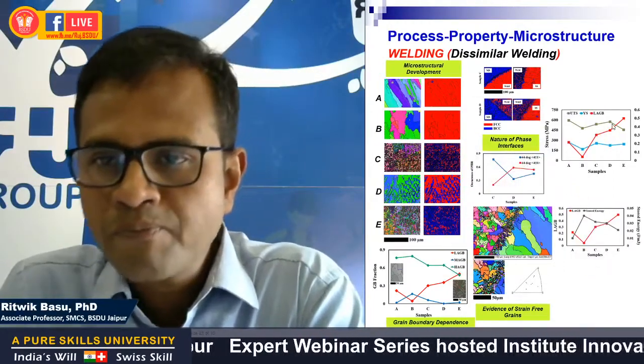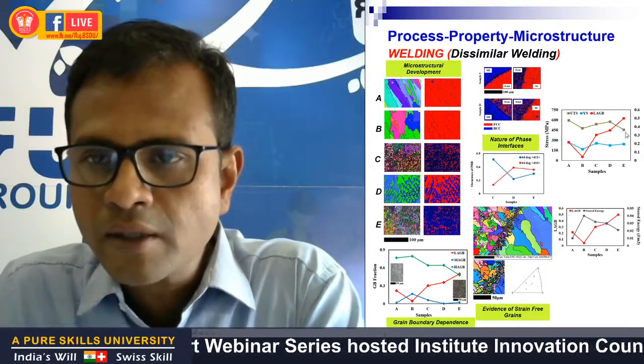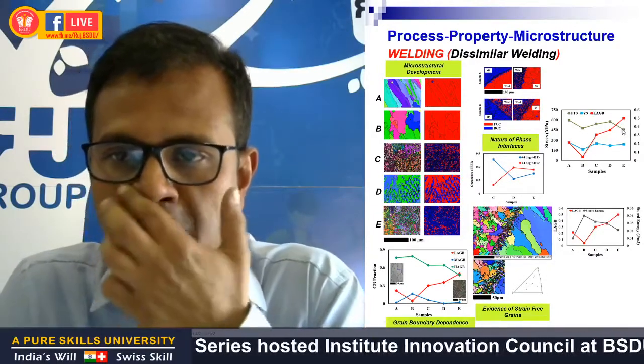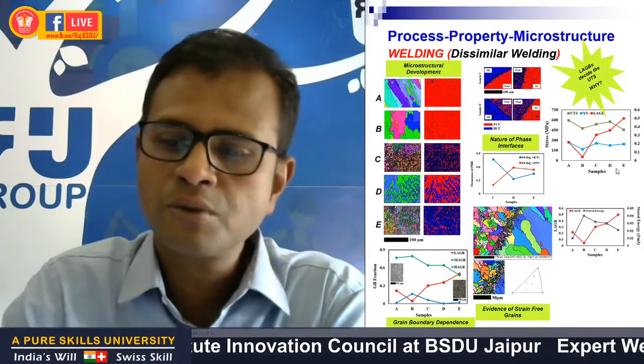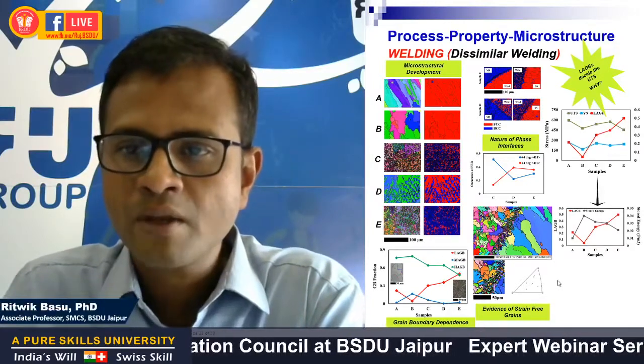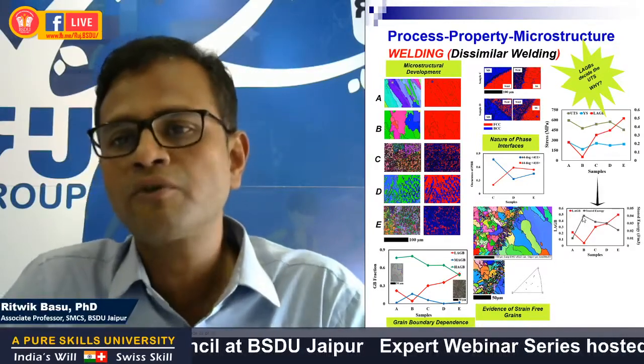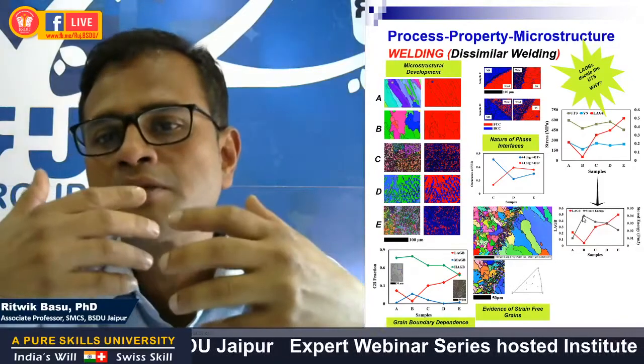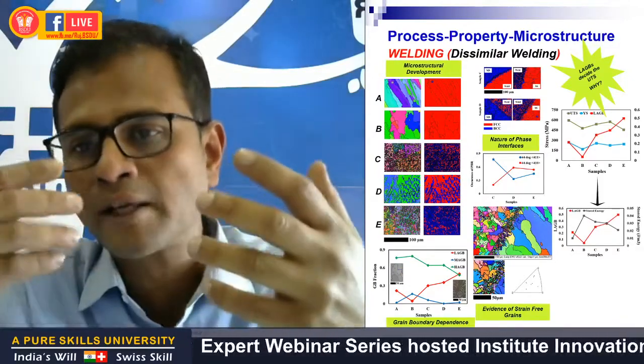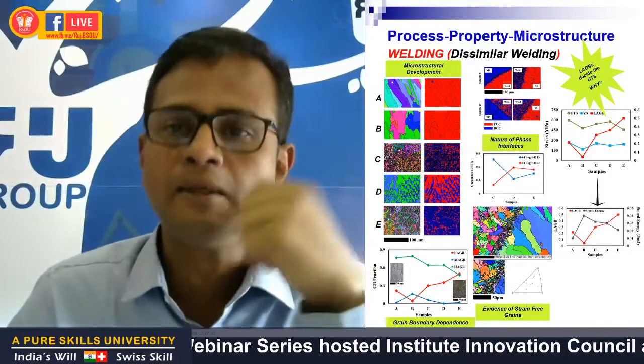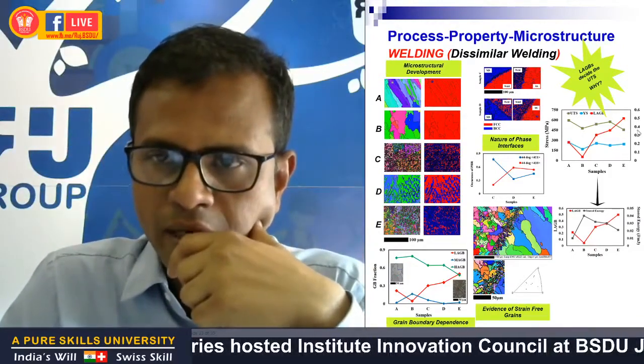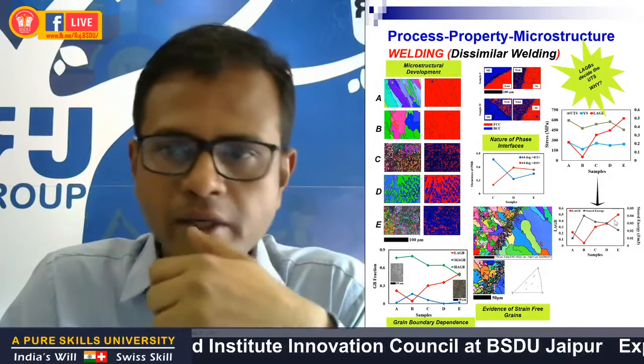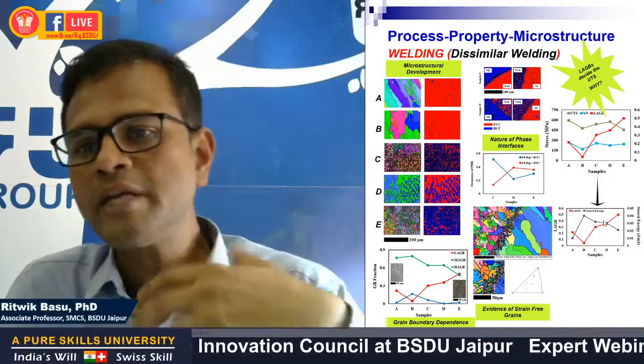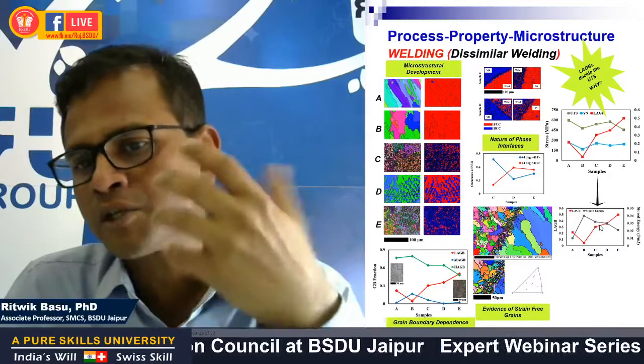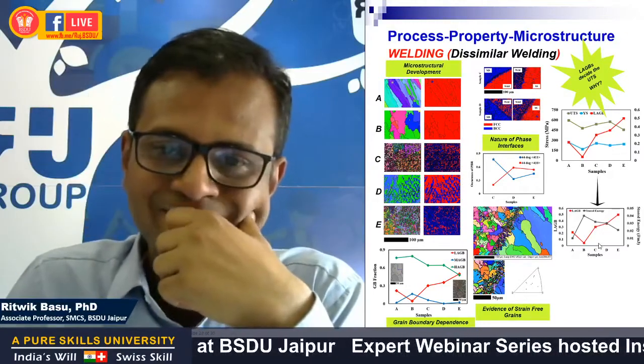So the decrease in the strength and ductility of sample E, as could be seen here, with an increase in the low angle grain boundary fractions, could be related to the lowering of the stored energy. And stored energy is actually the driving force that reduces the mobility of dislocations. And that led to early fracture even at lower stresses for sample E. So we found that the low angle grain boundary fraction correlates well with the stored energy estimated from the Read-Shockley equation, measured from the grain boundary misorientation criterion.